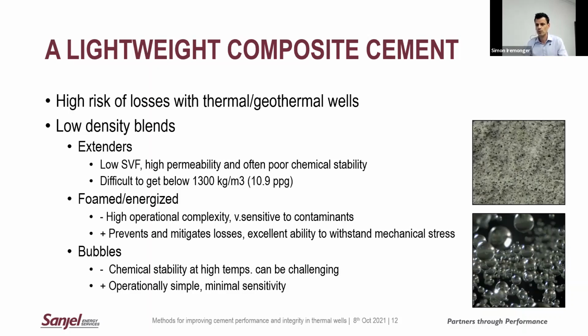A potential alternative to foam cement, maybe with some of the advantages still, is to use these glass microbubbles. And if you're not familiar with those, these are commercially available hollow glass spheres, low specific gravity, substantially below 1 specific gravity, quite small, sub 100 microns sort of thing. And so, some advantages there: operationally, it's quite simple. This is a conventional cement design, no extra equipment required to pump it, and similar to a conventional cement, minimal sensitivity. There are some potential downsides, the chemical stability, especially when we're dealing with the sort of high temperatures that we deal with on a normal basis.